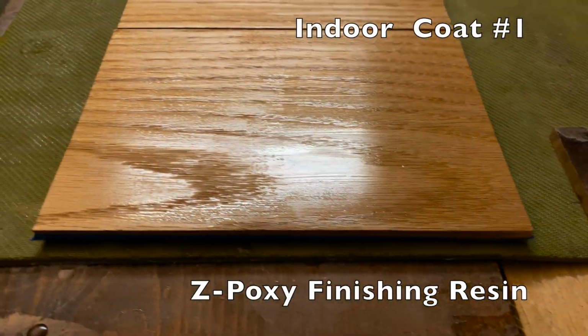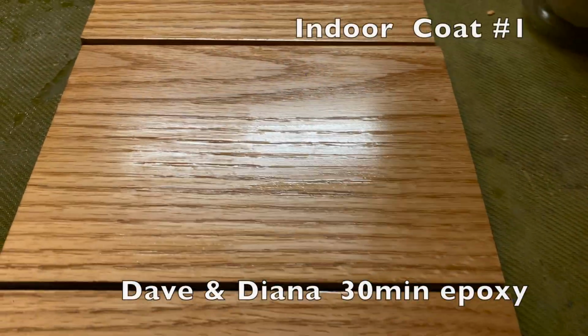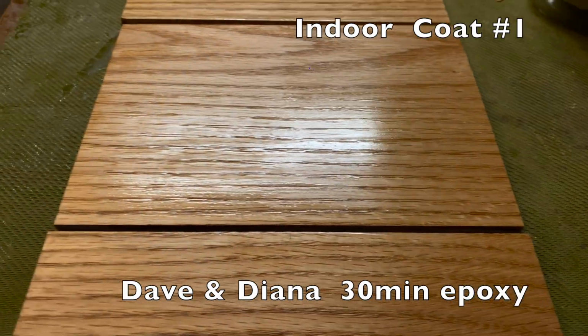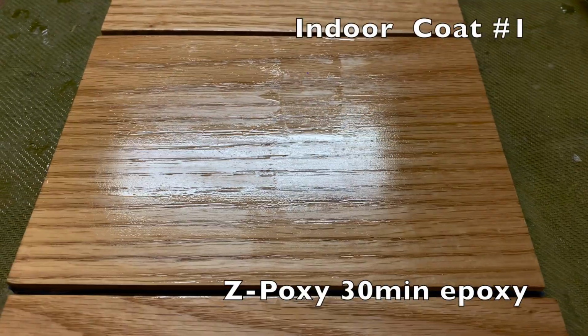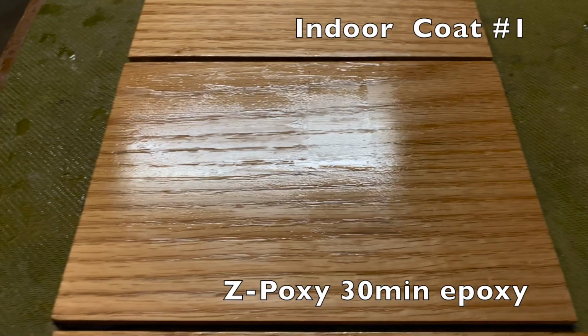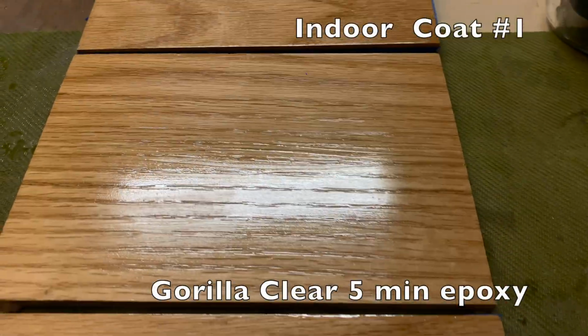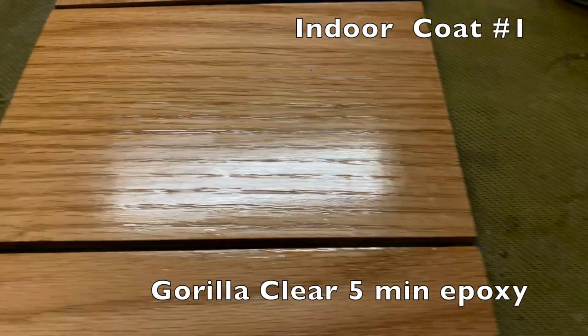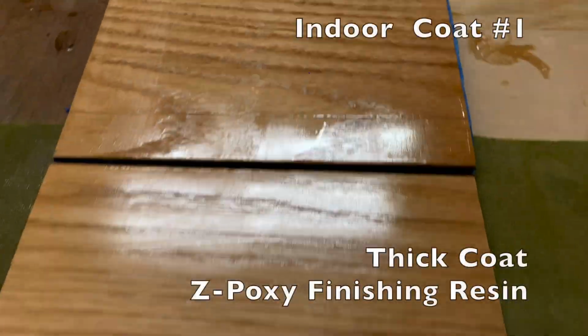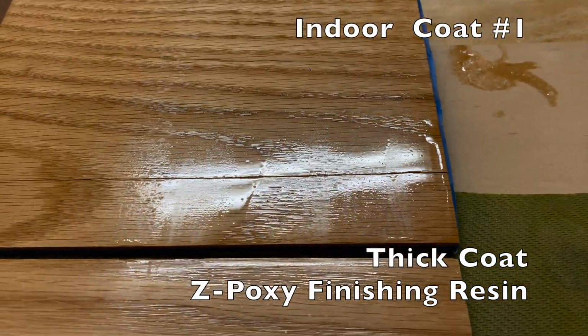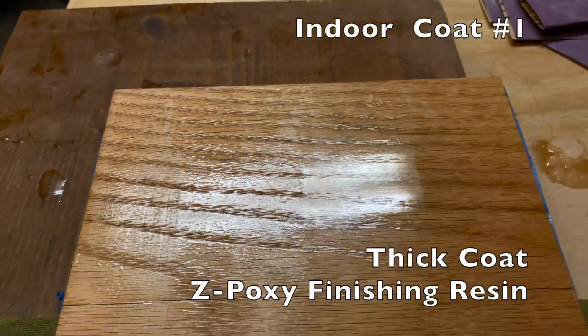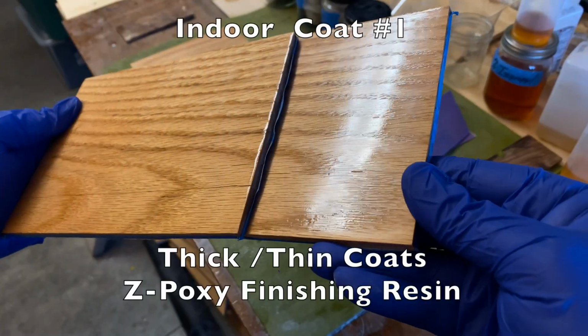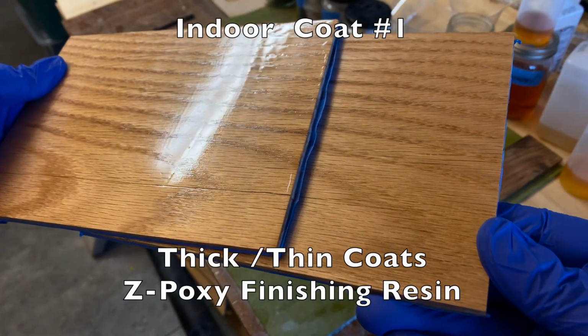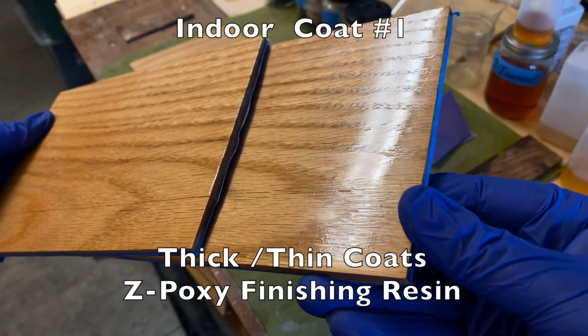Remember that the right side of each of these boards has been sealed with shellac, and again you can see where the epoxy has been absorbed more into the wood on the left sides. I was able to apply thinner coats this time around since the warmer temperatures lowered the working viscosity of the epoxies, with the exception of this one where I intentionally applied a thick coat. Here's a close-up of the thick and thin coat comparison using the Z-poxy finishing resin.